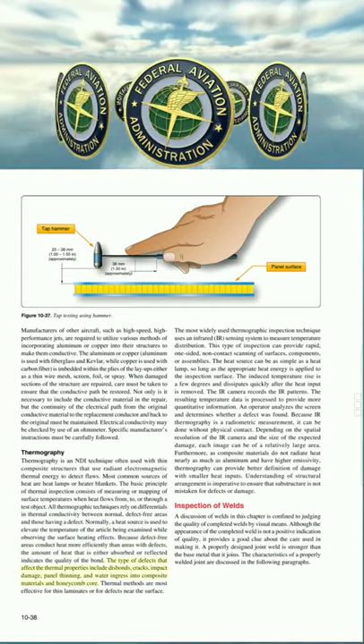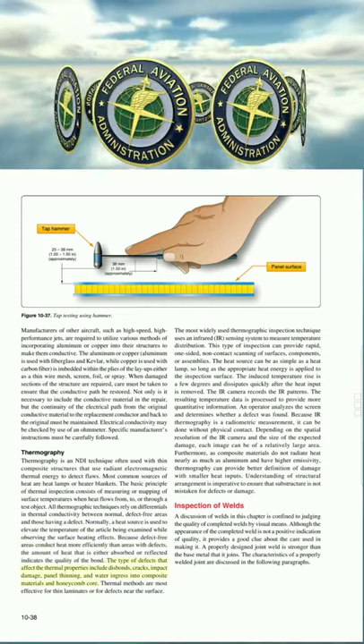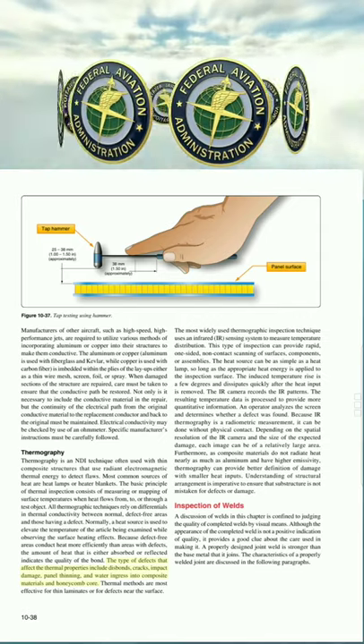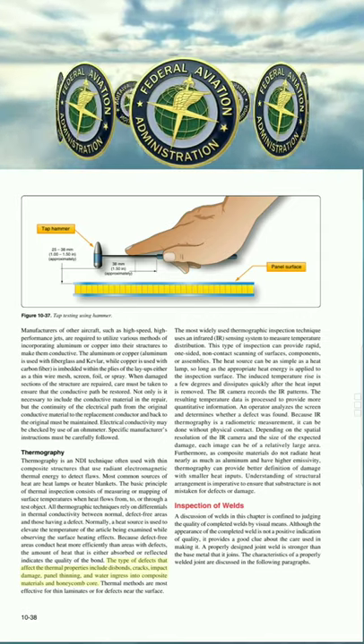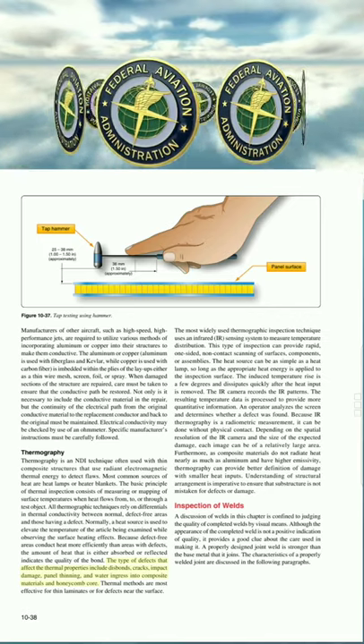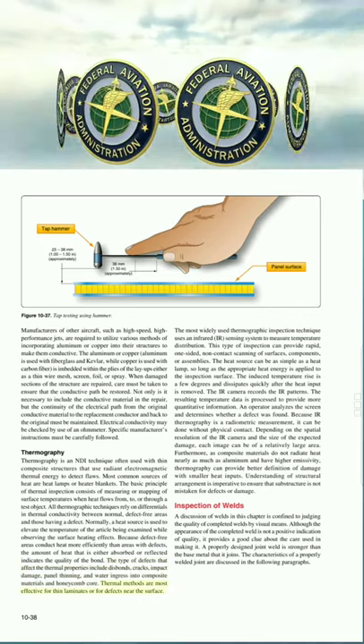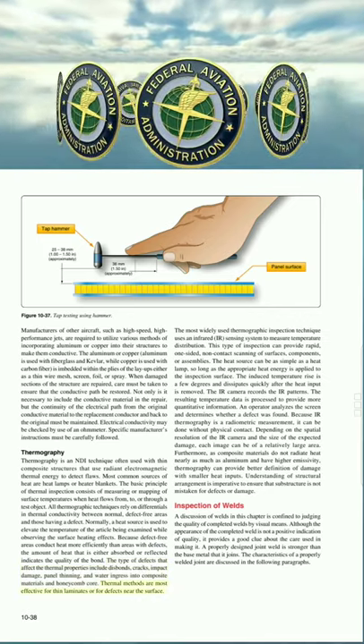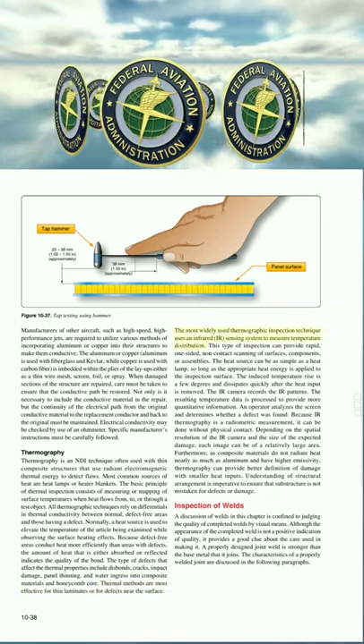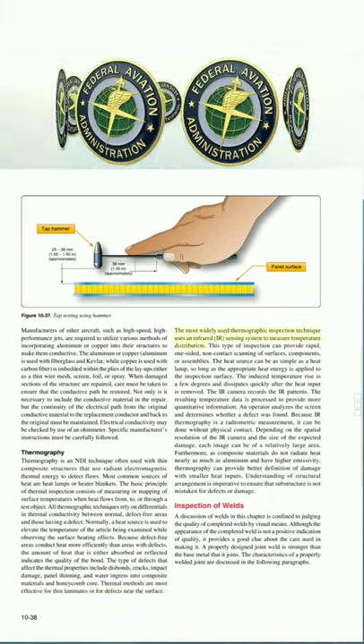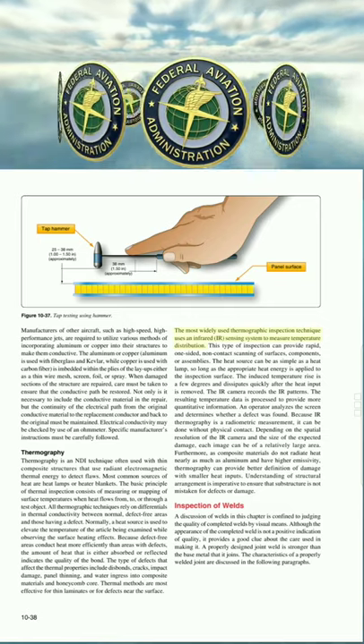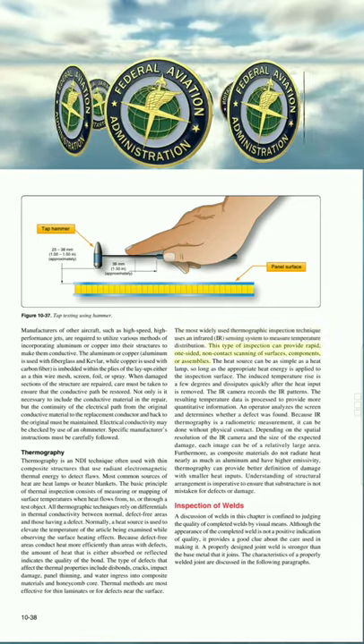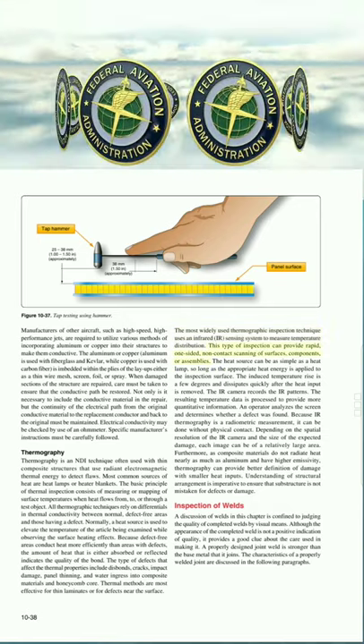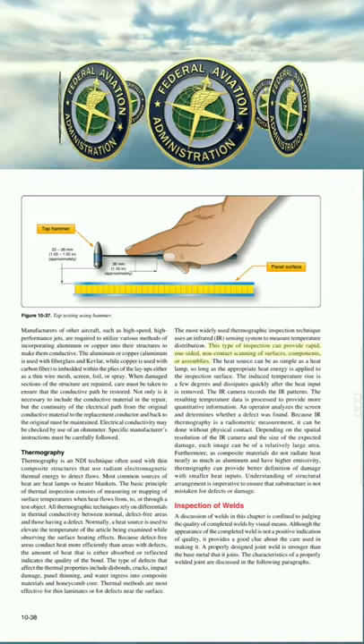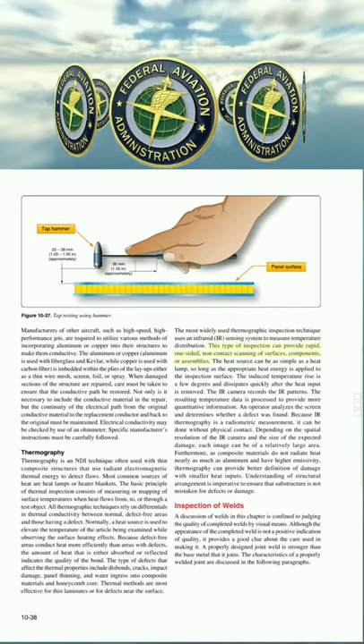The type of defects that affect the thermal properties include disbonds, cracks, impact damage, panel thinning, and water ingress into composite materials and honeycomb core. Thermal methods are most effective for thin laminates, or for defects near the surface. The most widely used thermographic inspection technique uses an infrared (IR) sensing system to measure temperature distribution. This type of inspection can provide rapid, one-sided, non-contact scanning of surfaces, components, or assemblies.